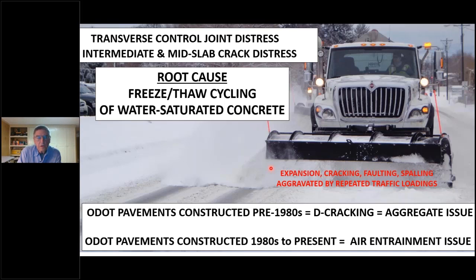So we're talking about cracking and spalling distress in control joints and mid-slab cracks. Prior to the 1980 construction, a lot of the problems were involved with decracking, which is, as it turns out, an aggregate issue. The root cause there, of course, is freeze-thaw cycling of the concrete while it's in a state of critical moisture saturation. We found that the same thing is true today, or at least I have in the work that I've done, that pavements constructed in the 1980s up probably to the present time. The problem is still involved with freeze-thaw cycling and distress associated with it. But in this case, it's an air entrainment issue, which I'll discuss.